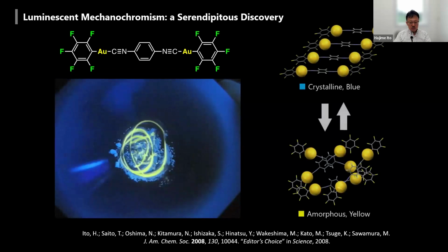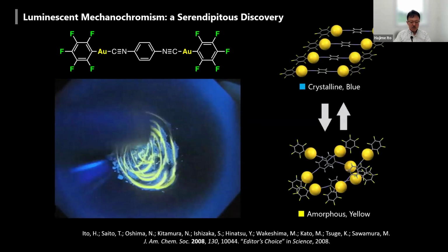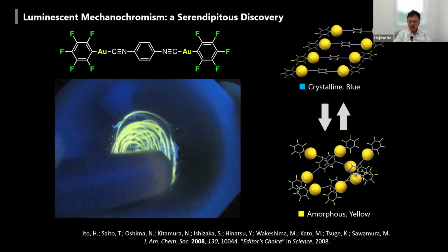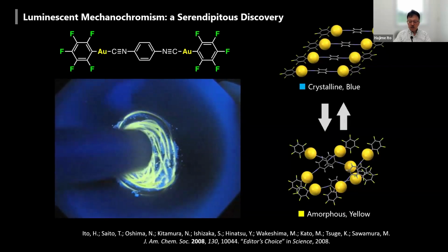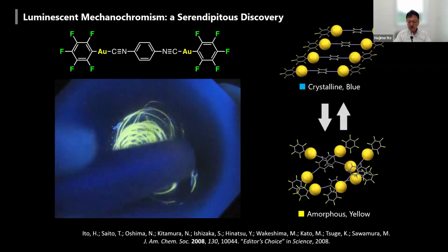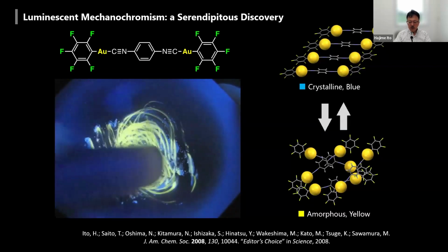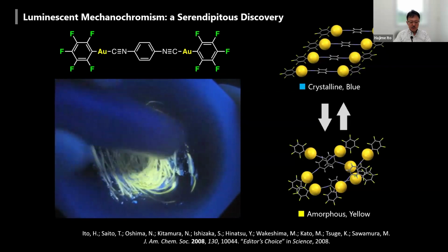This color change, we found, is based on the crystal structure change from a microcrystalline blue emissive state to a yellow emissive amorphous state, as shown here.